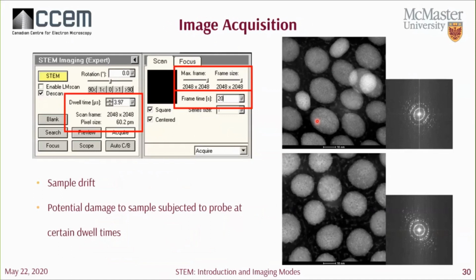I guess I should have discussed it earlier, but in this window you also choose the scanning rate or the dwell time of your image. The dwell time is the time that the probe is in a fixed position in order to collect data for one pixel. The total frame time is the total number of pixels multiplied by the dwell time for each pixel, which gives you the time required to acquire your image. So if you have a shorter dwell time, you'll be able to collect an image faster.